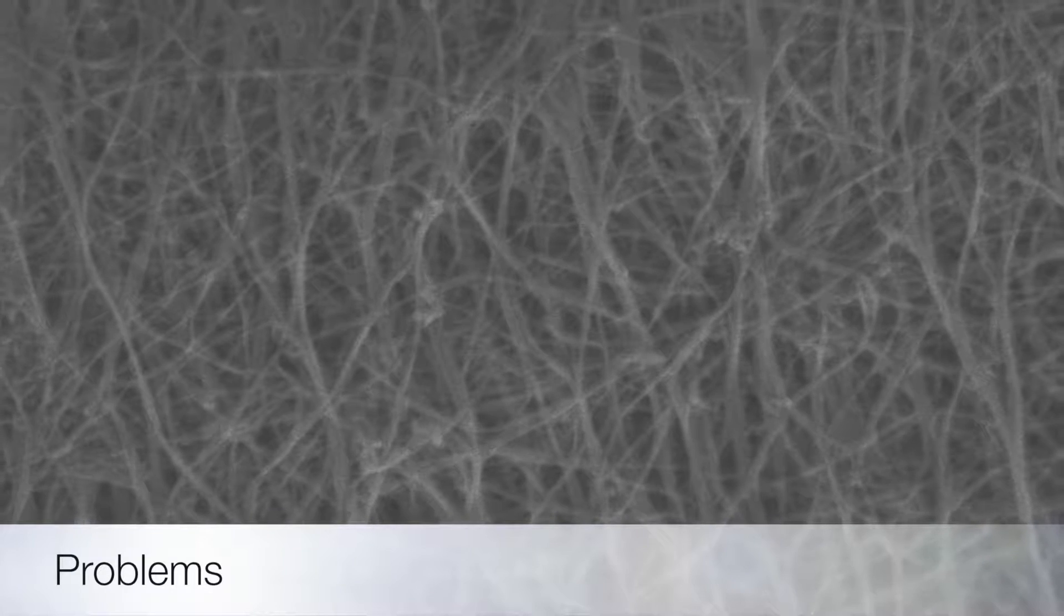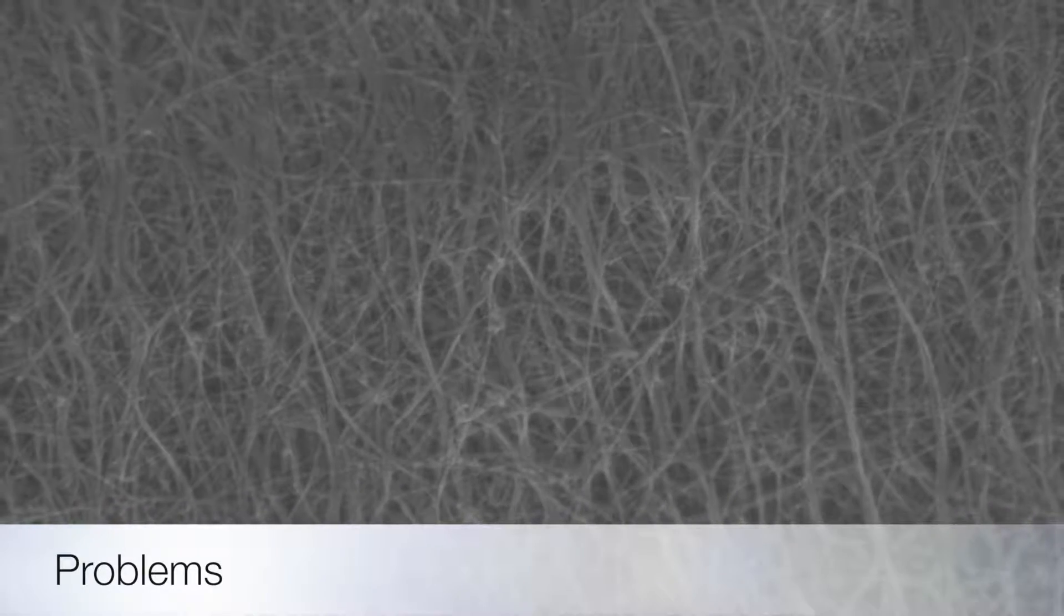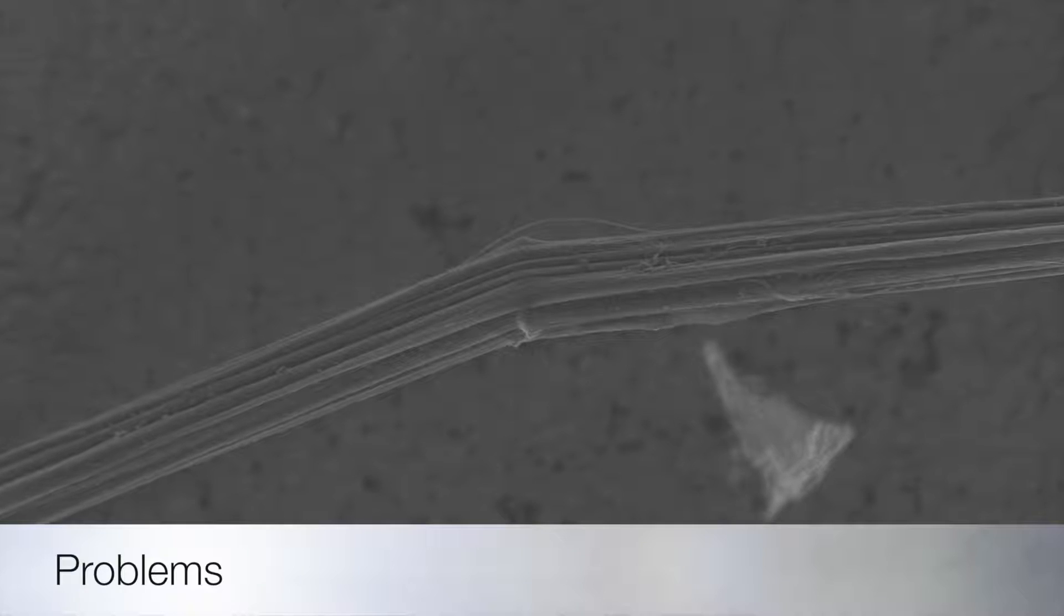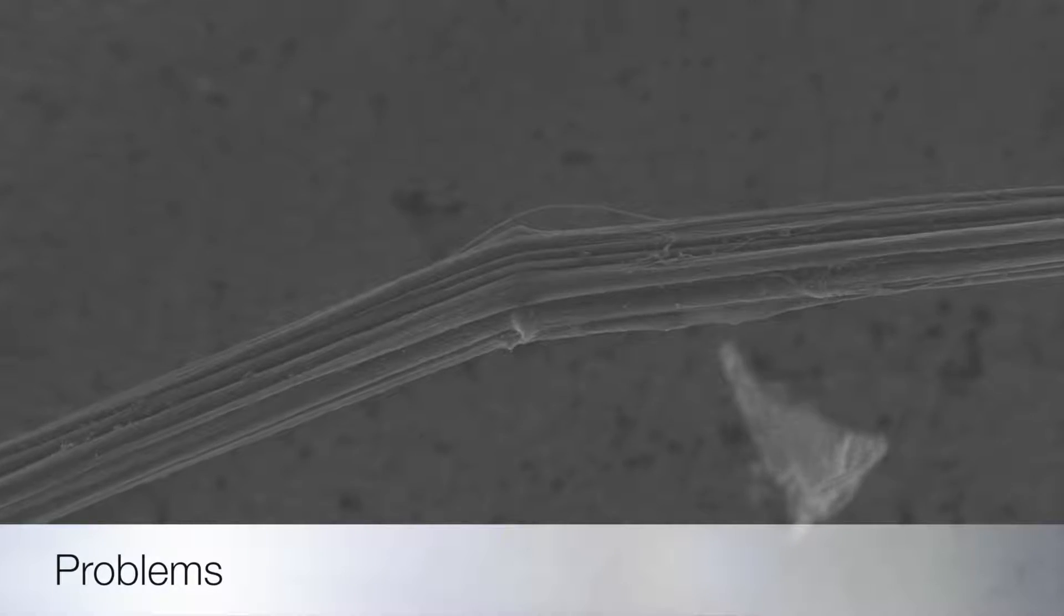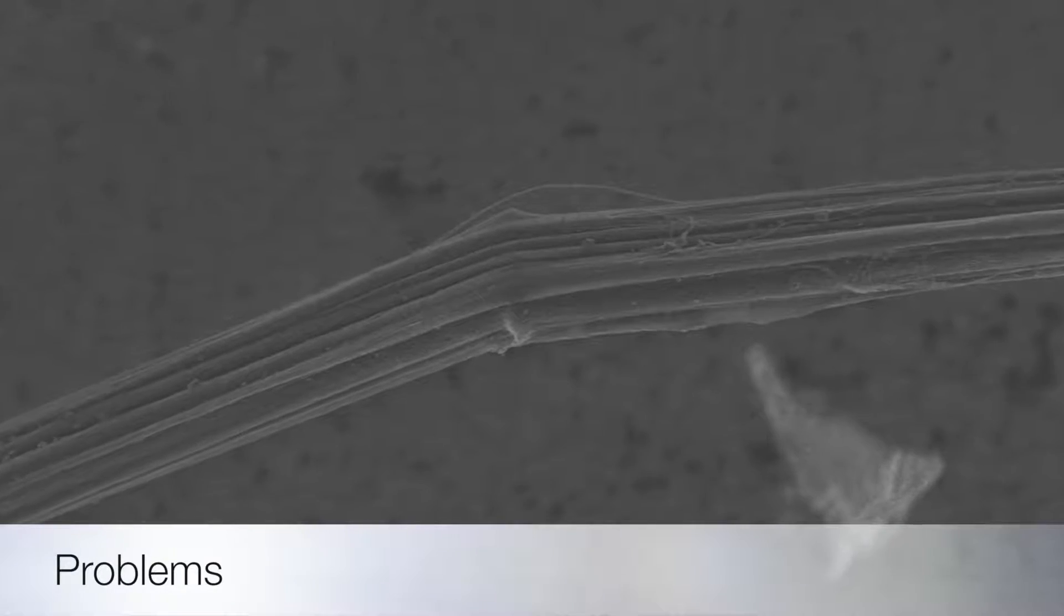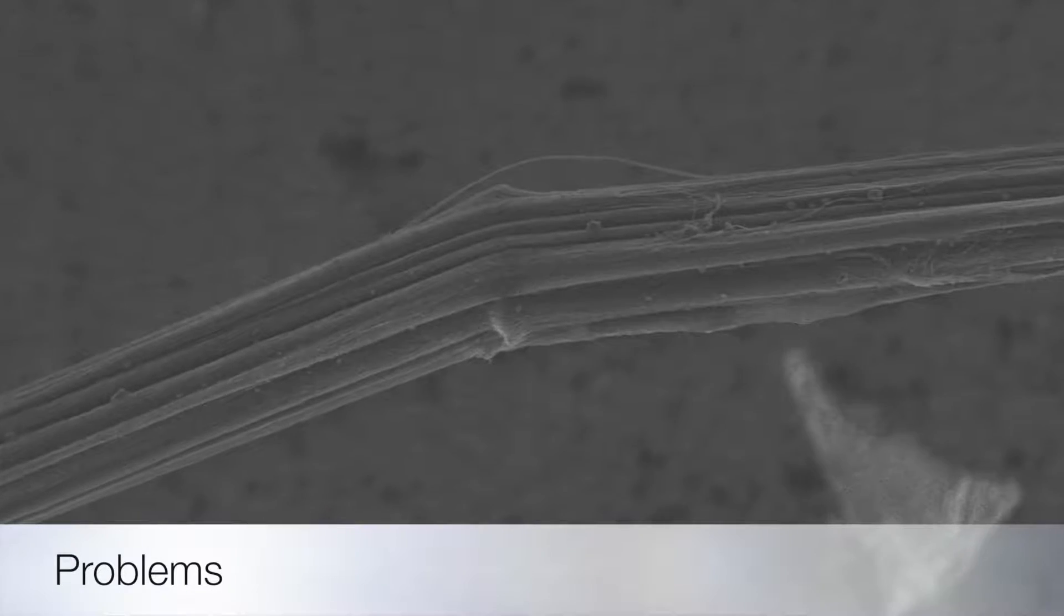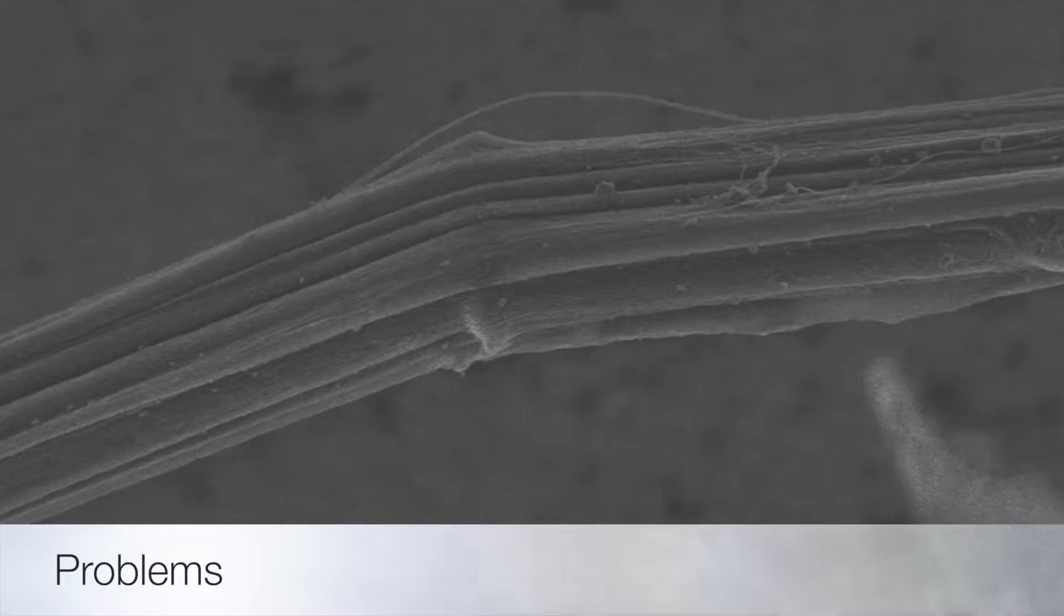Problems arise in great part by the material, as it has impurities, and up to today there is no way of controlling the chirality of the carbon nanotubes, so you'll always end up with a mixture of tubes with different properties. Another problem is the handling of these fibers and films. Because of their spinning process and storage, some end up having bends which will affect our field emission.